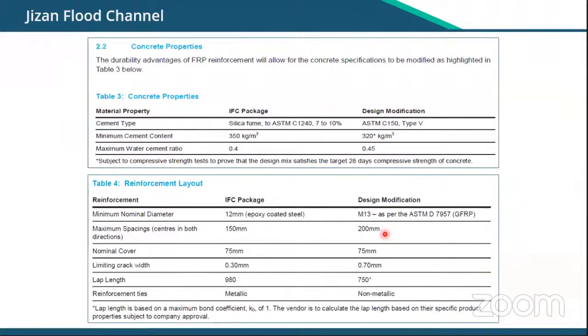One thing the designer didn't do on this project, and this is another example that it could have been improved further, is the concrete cover was kept at 75. For GFRP that is really conservative. Especially for the top part, it could definitely be reduced to 50 very easily. You can see also that lap length was reduced from about 1 meter in steel to 750 mm, and that's thanks to better bond strength.